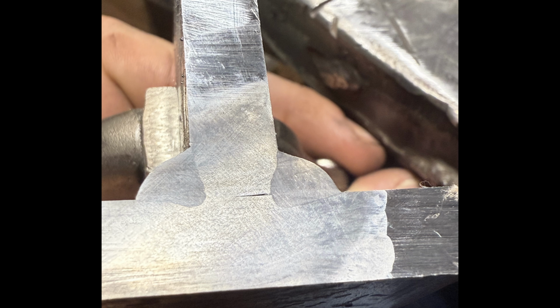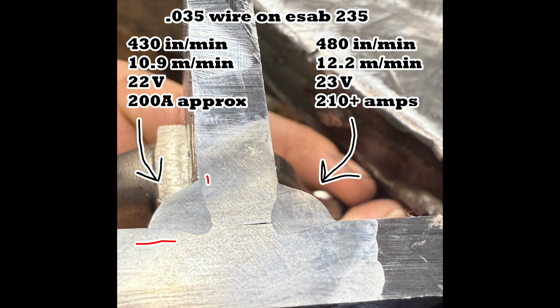The colder weld on the left side has a very straight, flat fusion line that's in line with the plate, and anytime you start seeing things like that, it's suspect that there's going to be a lack of fusion there. Keep in mind, this is one location cut and etch on this plate. The fusion will change depending on where you cut it on the plate. The closer you are to the start, the worse the lack of fusion will be. The longer you go, closer to the edge, it'll typically improve a little bit, simply because there's less metal to absorb the heat, and it will tend to fuse a little bit better. But the weld on the left I don't like. The weld on the right isn't too bad at all. Keep in mind, the one on the right was done at very high settings that are beyond any 200 amp home hobby machine. So you can see the settings there, and I highlighted the little areas with red that are suspect that I don't like, especially on the bottom of the weld on the left.